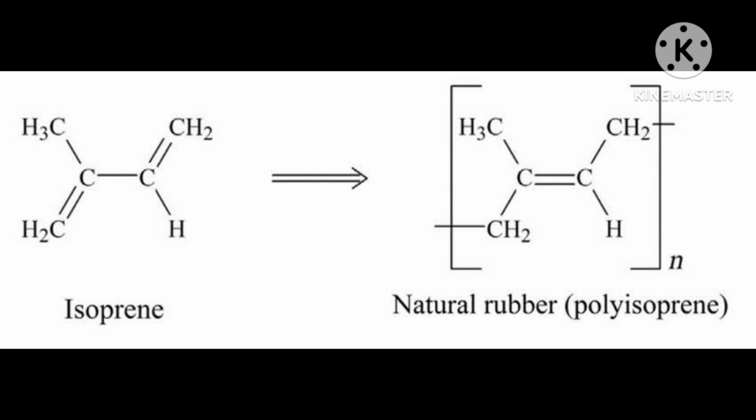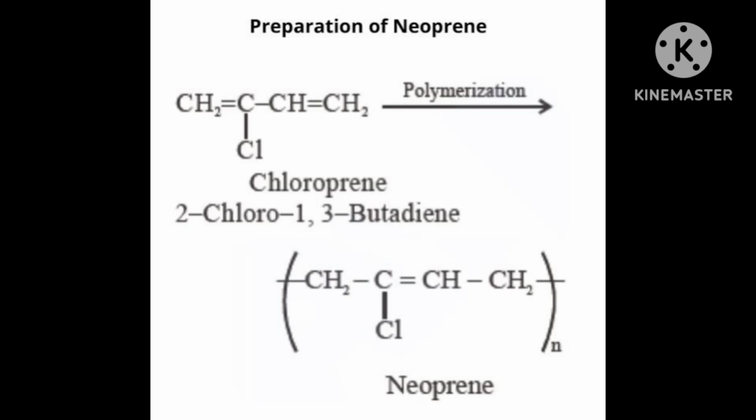And this isoprene is a unit. This will be repeated always. The isoprene unit will be repeated, then you will get polyisoprene. Correct? This is actually natural rubber, and it is also called cis-1,4-polyisoprene. Okay. And its structure you can understand very easily. That is the natural rubber structure.